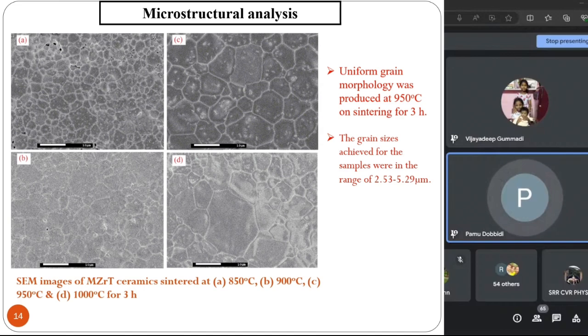As I showed you in the literature review, what is the difference between our work and the reported work? Here, what did we do? Literature is looking at 1400 degrees C and above. We are able to do it at 950 degrees C with a good compaction possible. We exploited nanotechnology in order to get a material which is highly densified and suitable for space application. That is the task that we have done. Can you go to the next slide, please?